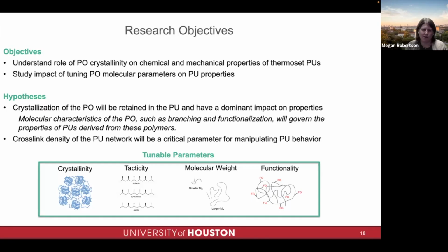In addition, this is a very tunable system. We can vary the extent of crystallinity in the polyolefin. If indeed we can retain crystallinity when we form this network, and we have polypropylene as a starting point, we could vary the tacticity. If we have polyethylene, we could vary the level of branching. We can also think about the molecular weight of the starting polyolefin and the degree of functionalization, both of which will impact the cross-link density of the cross-linked polyurethane that we form. So from a molecular design standpoint, there are a lot of aspects that we can look at.